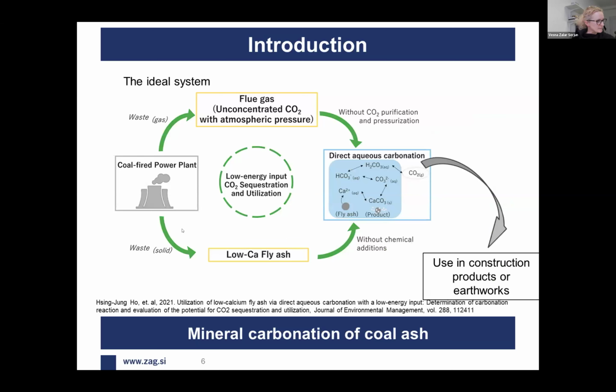The ideal system for the mineral carbonation of coal ash is defined here in this picture. It is taken from the literature, which is listed below. The ideal system is to use flue gases directly from their sources, and to use relatively low calcium fly ashes, which are the ones that cannot be used as supplementary cementitious materials. The further step would be direct carbonation, using either semi-dry or, even better regarding effectiveness, direct aqueous carbonation. In this way, the use of this material in construction products and earthworks was already shown. At least there is a path, but we have to achieve it on larger scales.